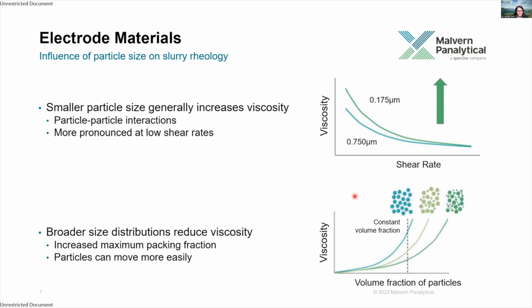And then as well as that, generally broader size distributions will reduce the viscosity of a slurry, essentially because you're increasing the maximum packing fraction. So if you increase the volume into which the particles can move more easily. So look at the bottom graph where we've plotted viscosity against the volume fraction of particles. If you have a monomodal distribution, then you'll have a higher viscosity for a given solid loading compared to if you have more variation in the particle size distribution, where we'll see lower viscosities.